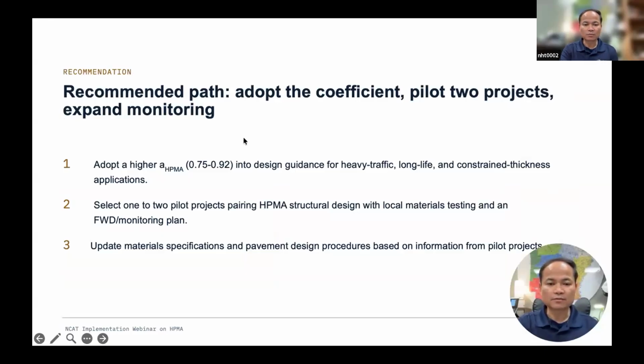So this will be the last slide for me. And you can see here our recommended adoption or implementation pathway for these technologies. In order for the state to justify the use of HPMA for structural pavement design, we believe that you should adopt a higher layer coefficient. And if you're in a state that uses pavement ME design, you need to do some fatigue cracking tests, and include that cracking resistance in the pavement ME design procedure. And if you're using perpetual pavement design, you can do the same, and then you can determine what we call the endurance limit when you design perpetual pavement.